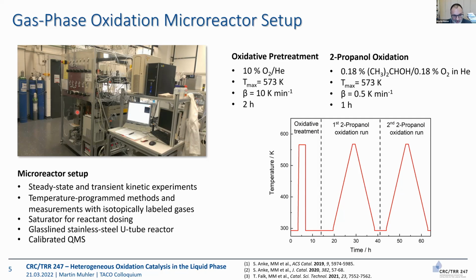It's a small U-tube reactor. We fill in 100 or 200 milligrams of sample. We pass gas through it. We try to establish plug flow conditions. And then we have a mass spectrometer that's actually behind the setup that is calibrated. And what I will show you in the following, that although it's a rather simple setup, you can perform really a multitude of different experiments, steady state ones, transient ones, temperature programmed experiments. You can dose liquids and so on. Key feature is this calibrated mass spectrometer.